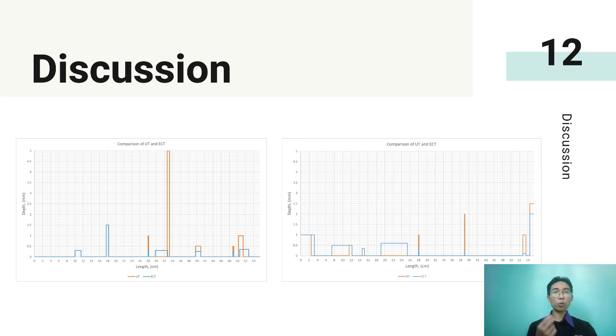Other than that, there are 2 more defects which were not detected by the ultrasonic inspection compared to the ECT inspection. This issue most likely happened because of the uneven surfaces of the pipe, which caused the ECT display to detect the gap of the uneven surfaces as a crack.